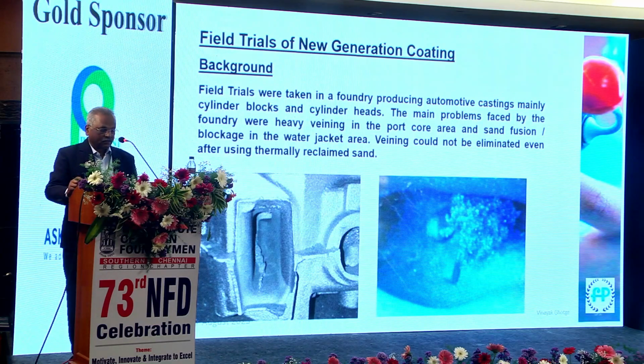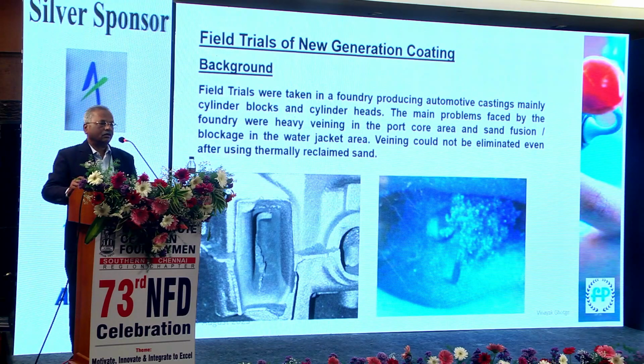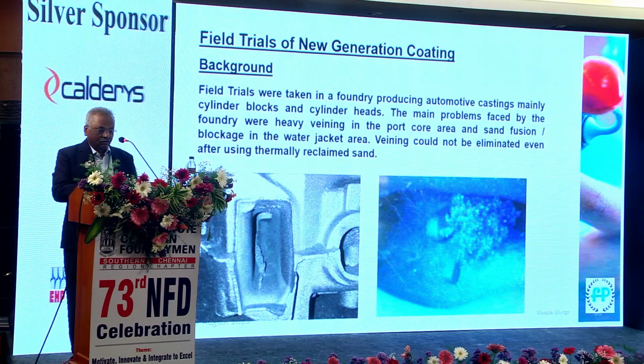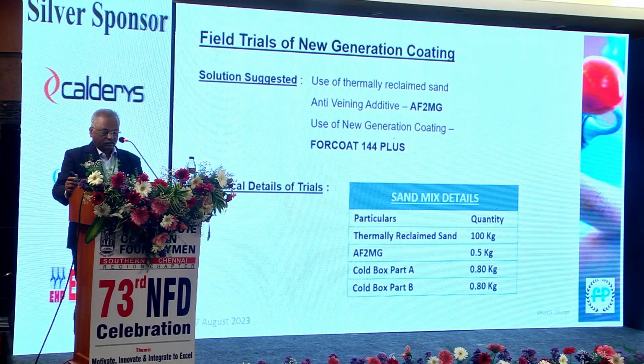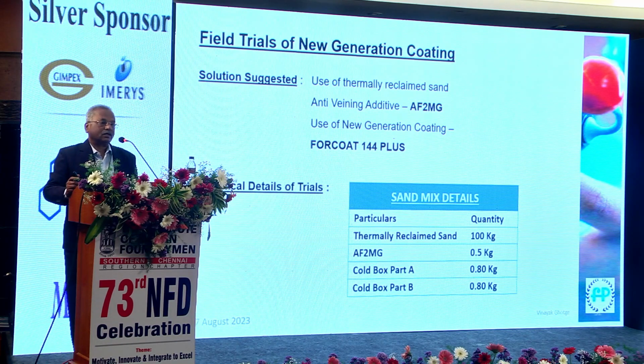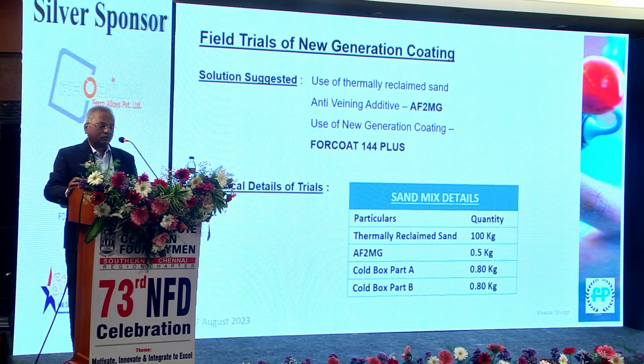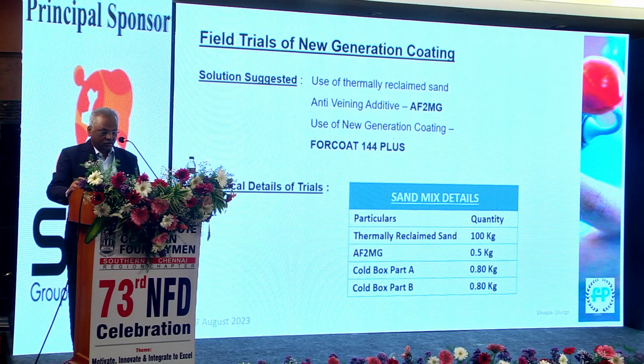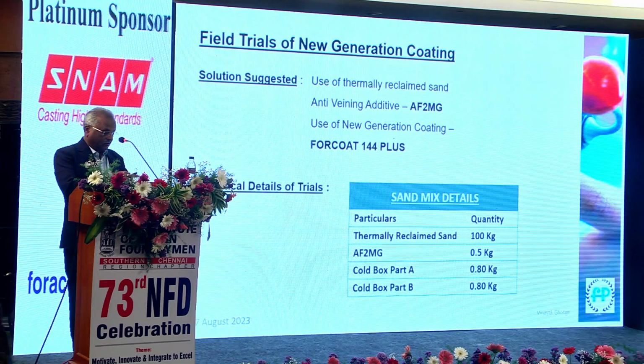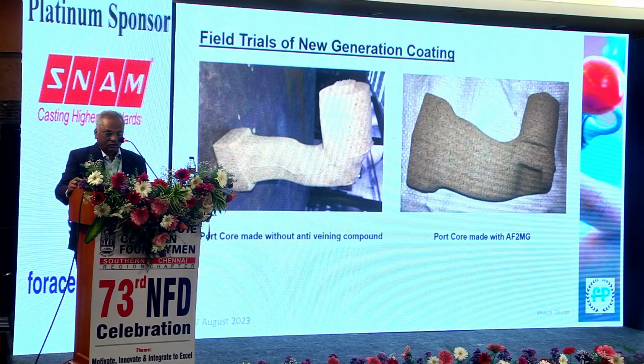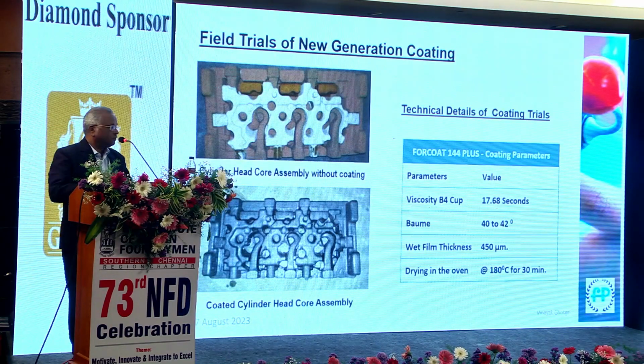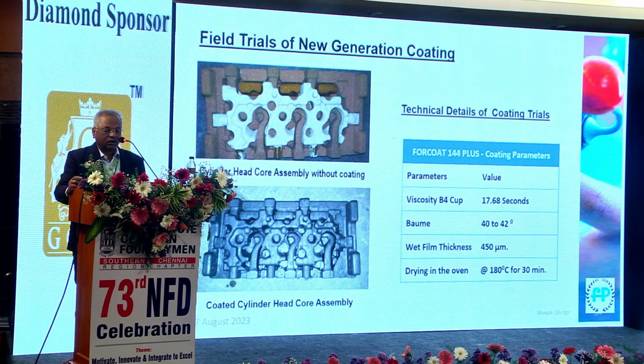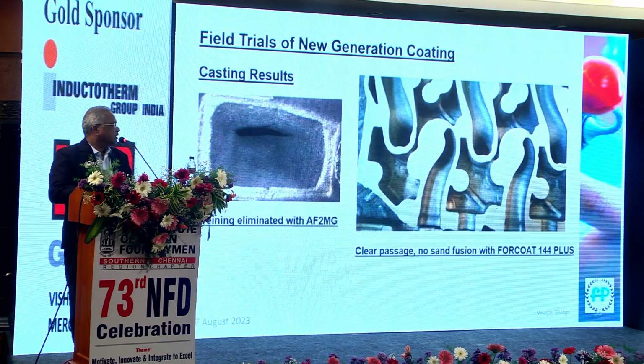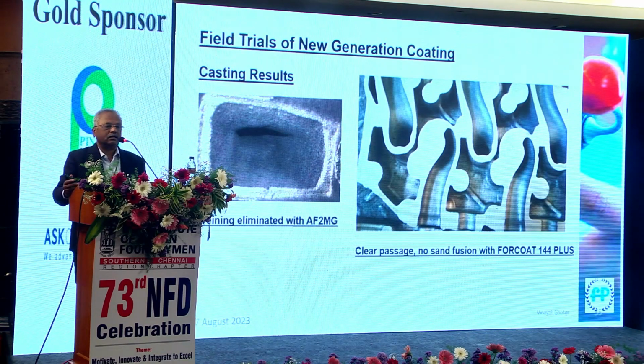This is a cylinder head casting at one of the foundries where they were having a problem of severe veining in the port core area, and there were also blockages of passages internally. So a trial was taken here with the combination of anti-veining compound as well as new generation coating. They were having a problem of, even though they were using 100% thermally reclaimed sand, still they were getting the veining. So there we used an anti-veining compound, and after making cores with it, we used the complete package with the new generation coating 144 plus, and this is how the casting feedback was. The cut section, you can see the cleanliness, no veining, no sand fusion.